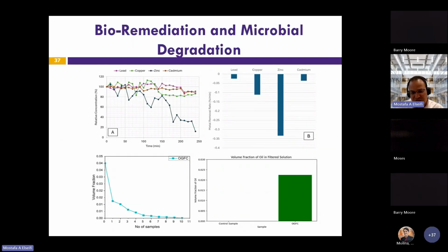In terms of biodegradation, what I'm showing at the top here is the degradation of these four contaminants, the four metals: lead, copper, zinc, and cadmium. We found that OGFC is very efficient in removing zinc and copper. You can see here the concentration of the pollutant over time. The zinc started at 100%, and at the end of the experiment, it was less than 20%. So again, we have very significant removal of zinc from OGFC.